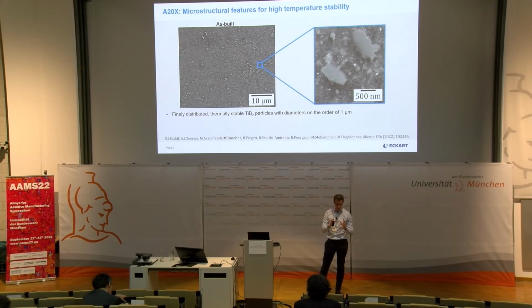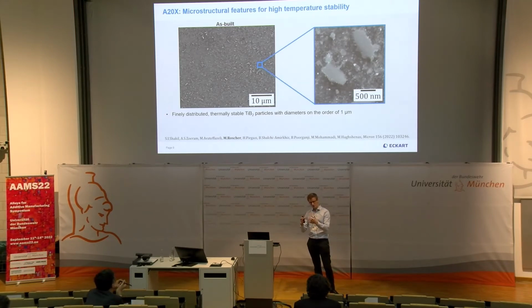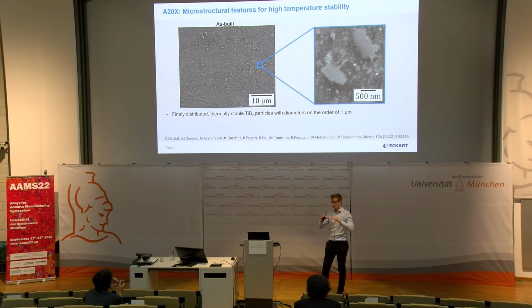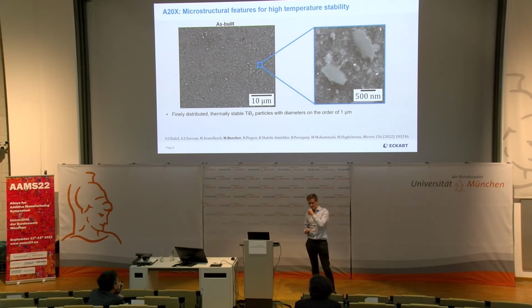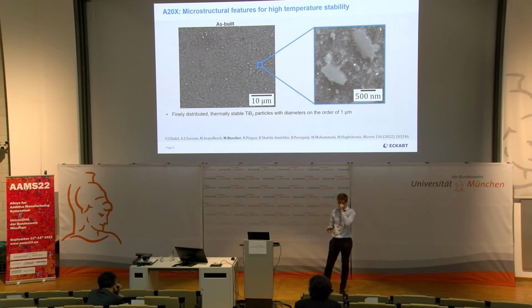And maybe a short anecdote that I can tell. We had a project related to Formula 1 motor racing, and there we had to modify the material. We had to bring down the titanium diboride content to comply with the regulations, from 4 to 5 weight percent, which is the usual range, to 2 weight percent titanium diboride. And I can say that reducing titanium diboride while keeping everything else constant decreases temperature stability with regard to strength. So titanium diboride definitely plays a role.